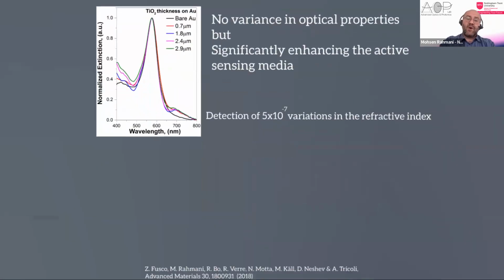But very briefly, what we did: we had ultra porous titanium oxide nanoparticles on top of nanostructures. Here, first we studied the effect of different thicknesses of these porous films. As you see here, for people who are doing sensing by plasmonics, they would appreciate that even 3 micrometers of this ultra porous film, I think 98% was the porosity of the films, doesn't really change the position of the resonance. Remember, a few slides ago, I mentioned that even one layer of graphene can change it, but here you see that the 3 micrometers of this ultra porous film on top of the metallic nanostructures doesn't make a huge change. But the good thing about this ultra porous film is that it increases the sensing volume, so that we can detect on the order of 10 to the minus 7 variation of the refractive index by this strategy.